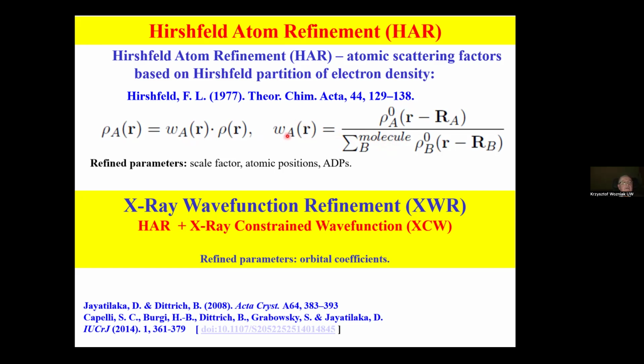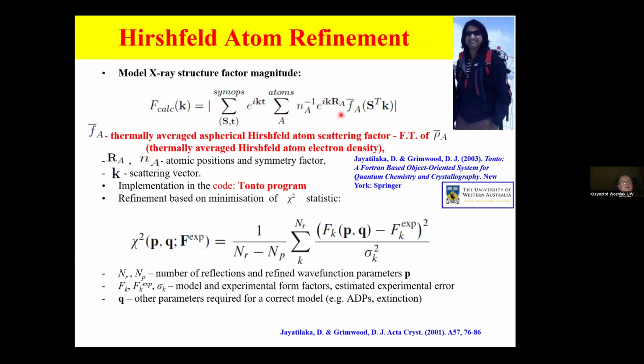And having this Hirshfeld partitioning done, we can Fourier transform this atomic electron density and get aspherical, thermally averaged Hirshfeld atom scattering factor, which is this F value here in this formula. And we can use this to calculate structure factors for our model of structure, similarly as we are applying pseudo-atoms after Fourier transformation. This approach was introduced by Dylan Jayatilaka from Perth, on this photo, who wrote a code called Tonto. And for a long time, Tonto was the only software allowing this kind of computations.